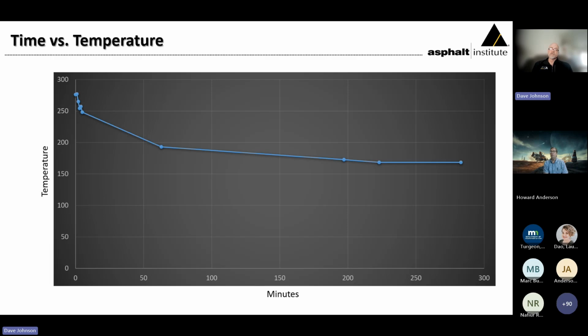Plus, this was done in July, hot temperatures. Air temperatures were going above 90 degrees at this time, fairly long days. And so it took quite a while for this material to cool off. On the positive side, because it takes that long, there is the potential to extend paving seasons, as well as the window of opportunity to get density is very wide as well.